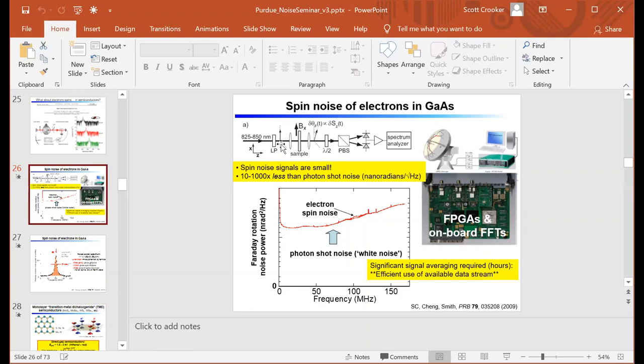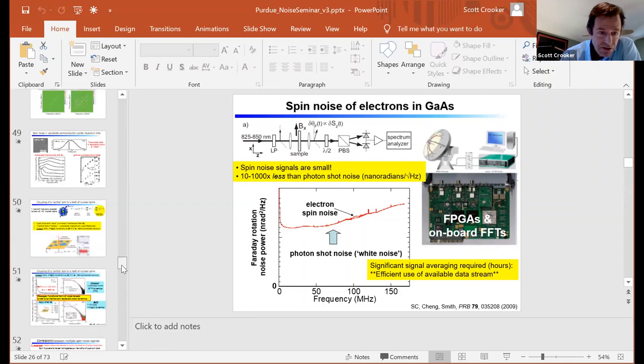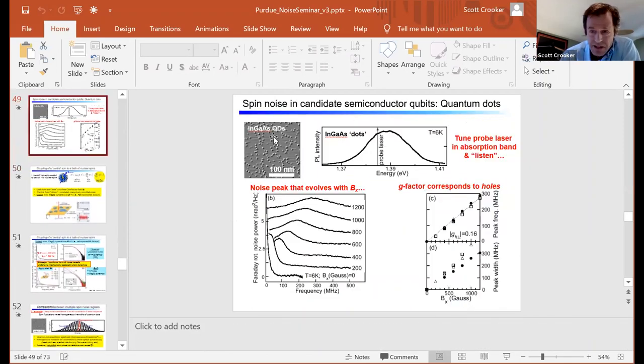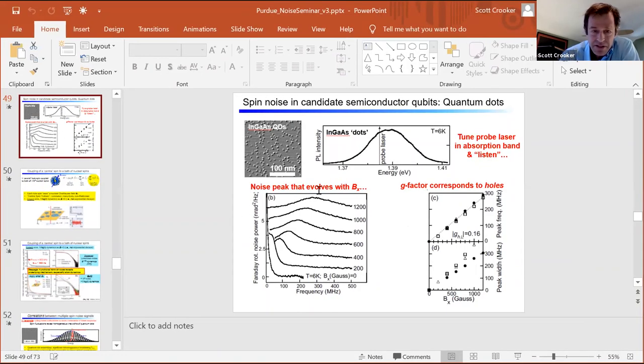So Scott, have you already measured spin noise from a single spin? You gave the impression that the smaller the system, the easier it is, the bigger the signal. Yeah, we did. This was years ago at a postdoc, with Yan Li, who is now a professor at University of Utah. We were looking at single semiconductor quantum dots, indium gallium arsenide quantum dots, and we were able to isolate single quantum dots that were doped with single electron or single hole spins and actually get signals from them. We never published any of that work because that experiment was done earlier by the Hanover group, but it's definitely possible to measure fluctuations from a single spin. The challenge is really just isolating a single spin and having multiple optics to make sure that you're just looking at one.